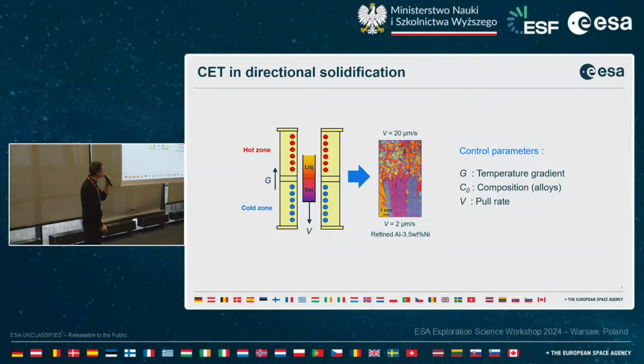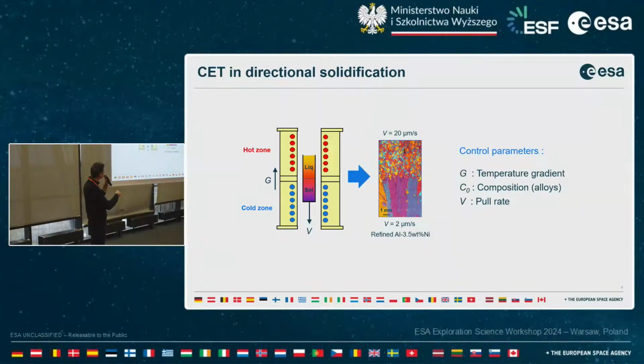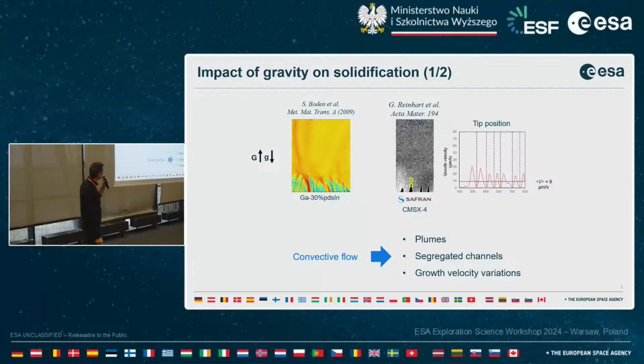So it's a good way to control the solidification, and you can see here a nice illustration of a CET that was obtained using this technique, where you have columnar grains for a low pull rate of 2 microns per second, you can see nice columnar dendrites. And then after increasing the pull rate by a factor of 10, it triggered the nucleation of new grains and a columnar to equiaxed transition happened. Well, that's the main idea, but obviously things are not that easy in real life, mainly on Earth due to the occurrence of gravity-related effects that I previously mentioned.